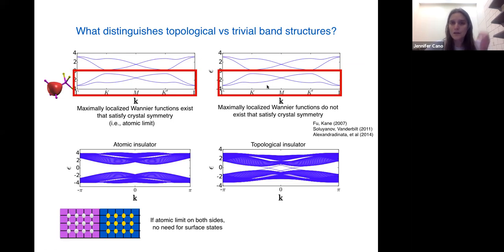And so if you have an example in your head, say think of bismuth selenide, where the bands are inverted at the gamma point. In bismuth selenide, at the gamma point, the bands have a P orbital character, but at all the other TRIM points, they have an S orbital character. So there is no real space Wannier function that can capture both of those symmetries at once.